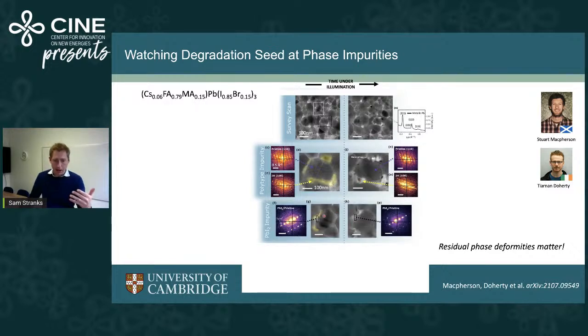We can see that also with lead iodide. So this is an example where we have, in fact, epitaxial lead iodide on these grains. And again, it's those before and after illumination, so after is on the right. We see material loss and again, also some metallic lead that forms.